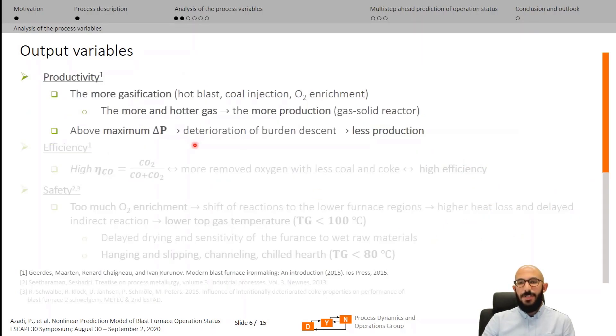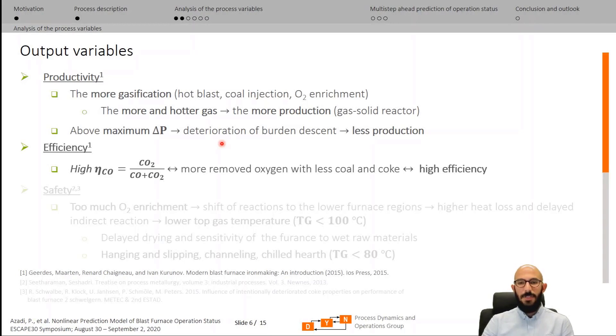As learned in the process description, the more gasification happens as a result of higher injection of hot blast air, coal injection, and oxygen enrichment, the more gas is produced, the more reaction between gas and solid bed occurs, and therefore the more hot metal is produced. The maximum threshold of pressure drop is typically identified by the geometry of the blast furnace, varying from 1.4 to 1.7 bar from one blast furnace to another. Exceeding the maximum pressure drop deteriorates the burden descent, implying less production. The efficiency of the process is identified through the gas utilization factor eta-CO, which is the ratio of carbon dioxide in the carbonaceous portion of the gas phase — the higher this value, the more oxygen removed with less carbon-based materials, and therefore the more efficient the process.